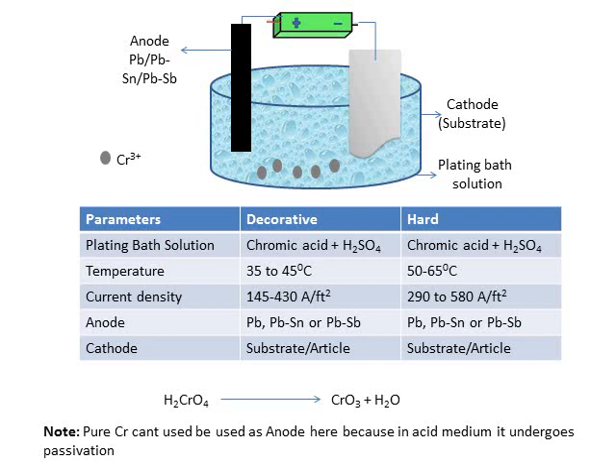Interestingly, pure chromium is not used as anode here, as we have discussed in the previous slides. Because if pure chromium is used as anode in the acidic medium, it undergoes passivation, meaning an oxide layer of chromium will be deposited on the surface of the chromium. Hence, it leads to poor deposition. So, as a result, insoluble anodes like lead tin alloy or lead antimony alloys are used as anode here.